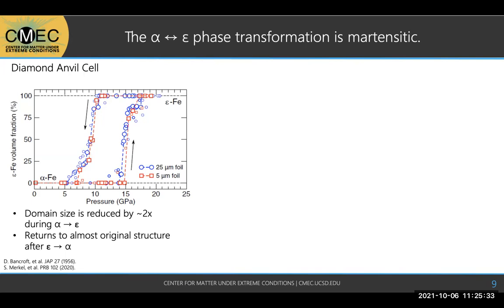And they produced this really nice hysteresis curve that I really liked reading about, because it shows, during compression, how the epsilon phase starts nucleating until you get to 100%. And then as they start releasing pressure, you see how the alpha phase starts nucleating back. And it's not a perfect hysteresis curve. It doesn't occur exactly at the same pressures during compression and release. It actually happens at different conditions.